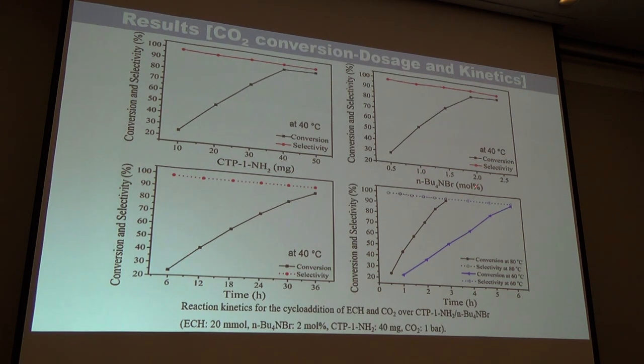the tetrabutyl ammonium bromide loading was tested from 0.5 mole percent to 2.5. We can see the conversion also increased here linearly from 0.5 to 2 mole percent, and then it is saturated. So the optimum values here are 40 milligram and 2 mole percent of this tetrabutyl ammonium bromide.